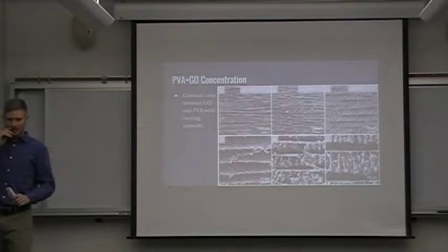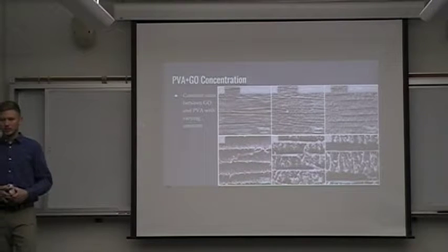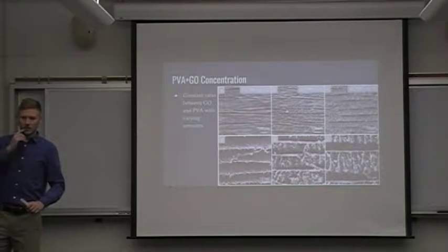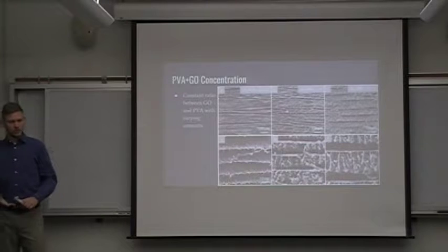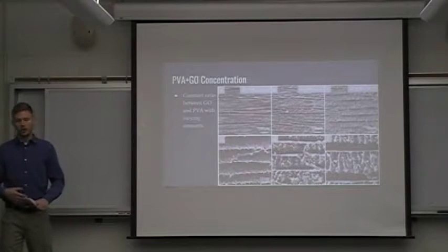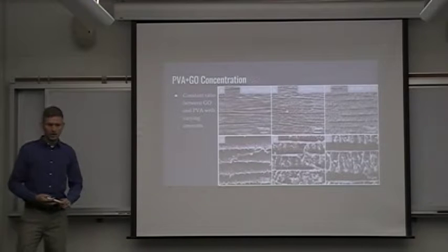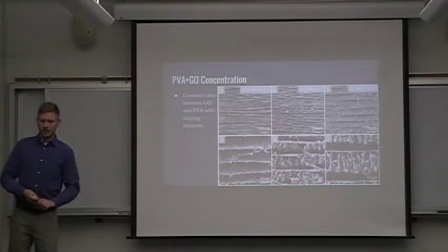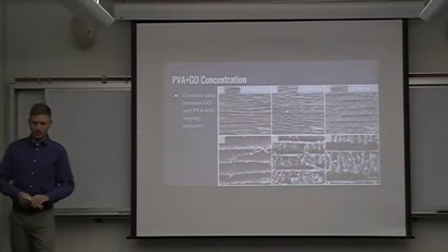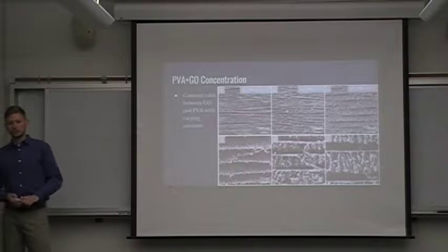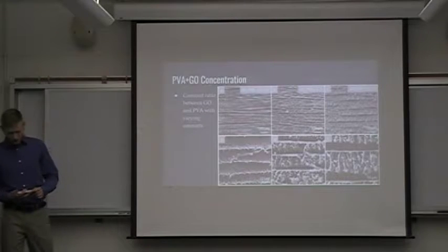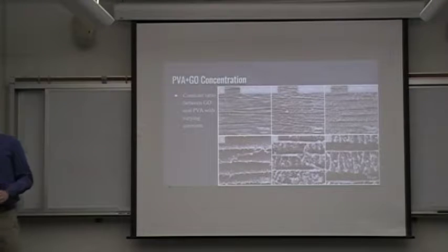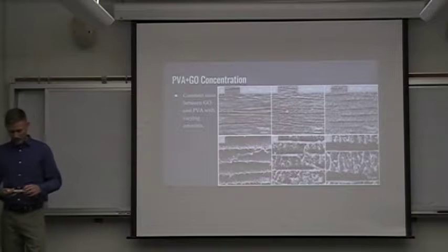The high density, as the ice nucleates in various positions throughout the aerogel, it is competing with itself on whether or not it should create another ice crystal, or should it build on the already existing ice crystal. And the density blocks, so you have the graphene and the PVA blocking the water molecules from each other, and that can cause the various ice nuclei to not form or form on the existing ones.